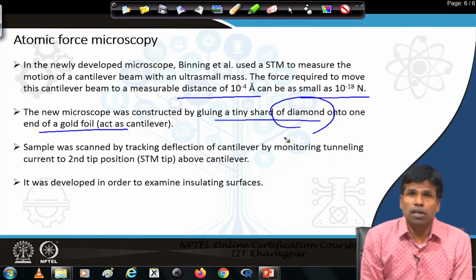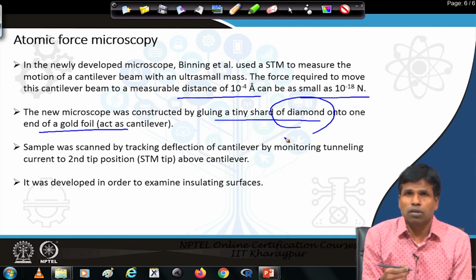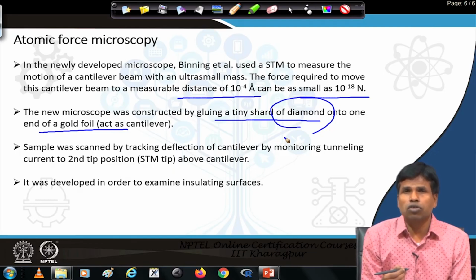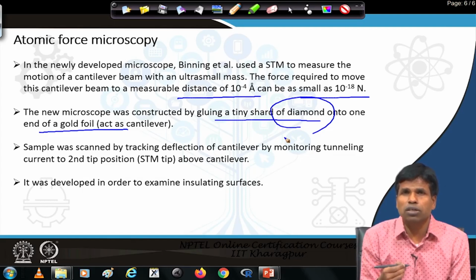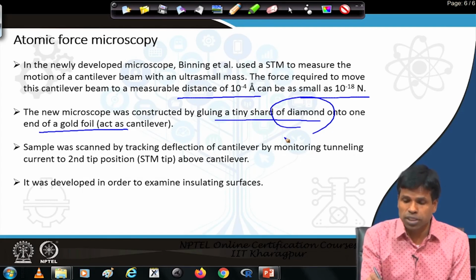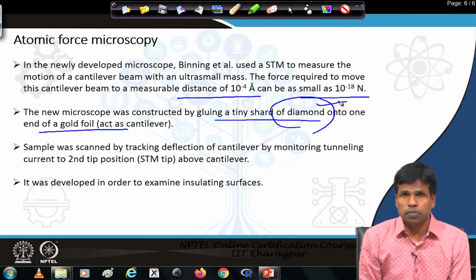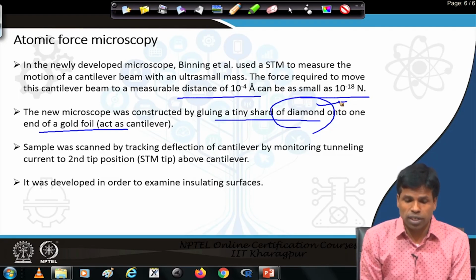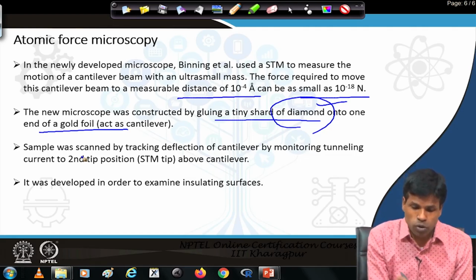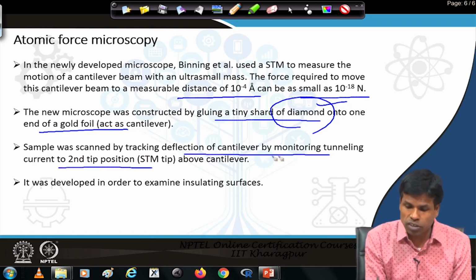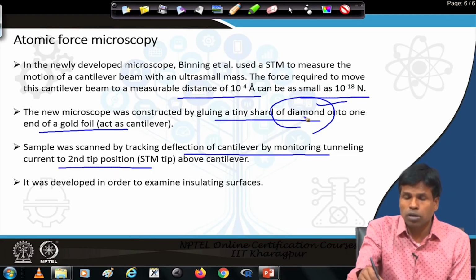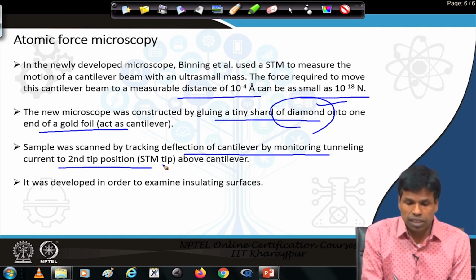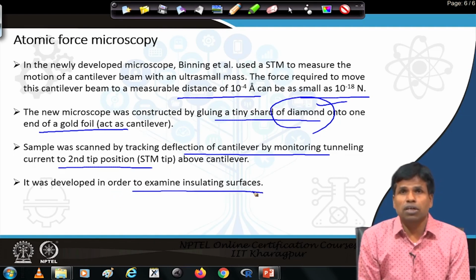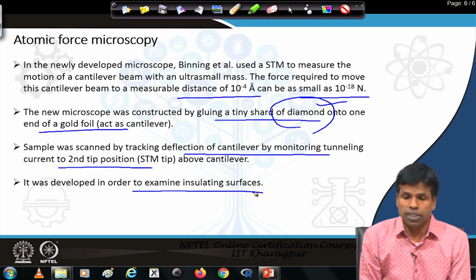As you know, in the scanning tunneling microscope, the tip is made of tungsten or platinum-iridium. Those are metals, because we need to measure the tunneling current between the tip and sample. The sample has to be conducting or semiconducting, and the tip has to be metallic. In this case, as you see, the tip is no more conducting, neither metal nor semiconductor. It is a diamond, which is insulating. So, using a diamond tip, they scanned the surface and tracked the deflection of the cantilever by monitoring the tunneling current using a second tip above the cantilever and diamond assembly, and using that they have successfully examined insulating surfaces and created the surface topology of insulating material.